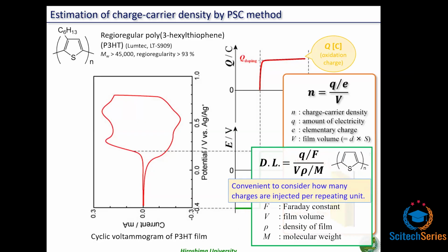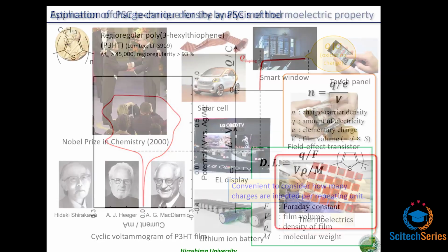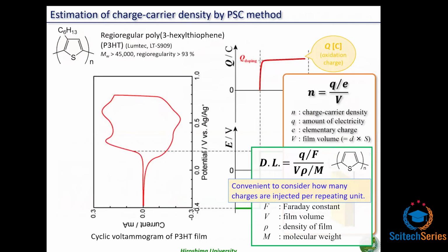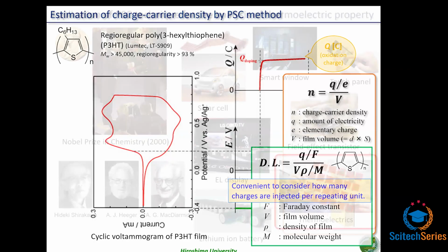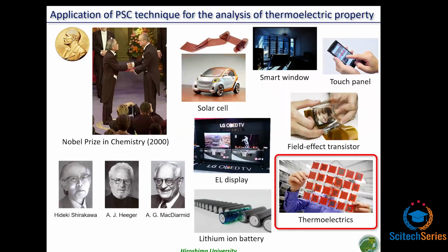And finally, the charge carrier density can be calculated from this equation using the amount of electricity estimated from PSC analysis, the elementary charge, and the film volume calculated from the film area and the thickness. By applying the technique for quantifying charge density using PSC method, we analyze the thermoelectric properties of conducting polymers in relation to the charge density.